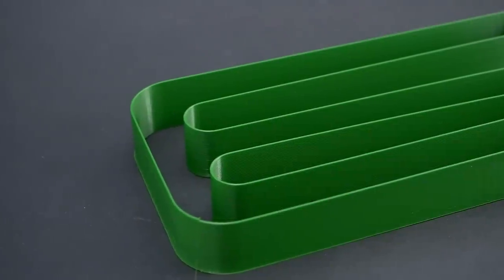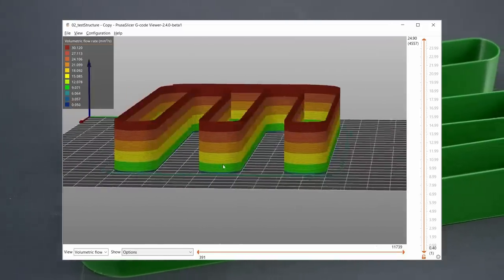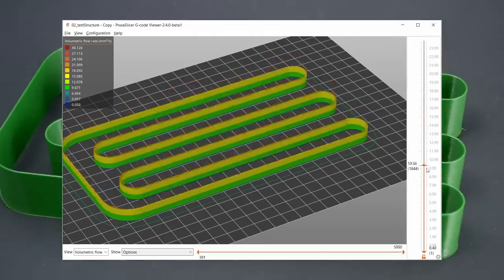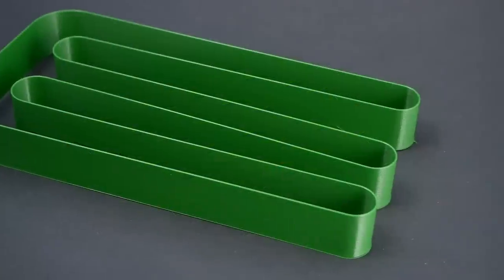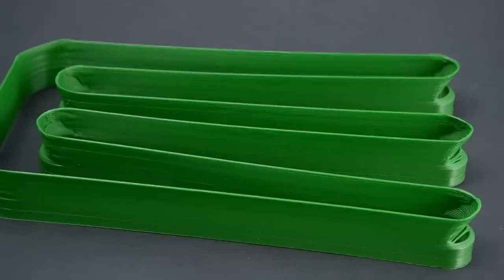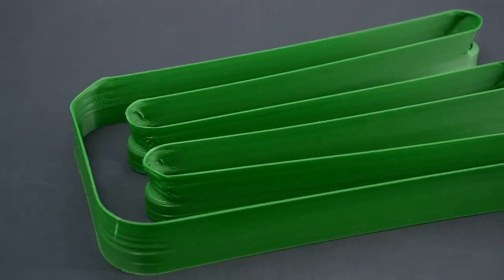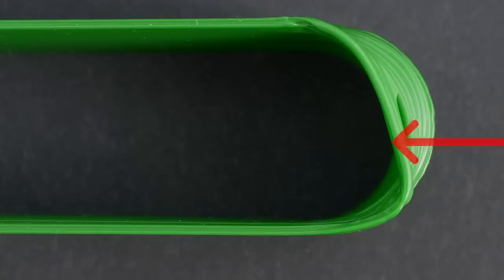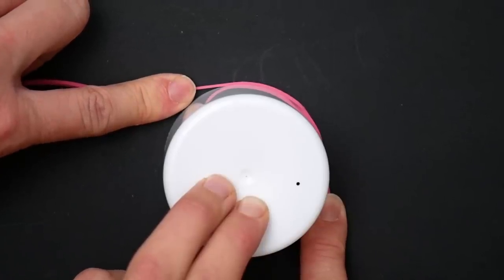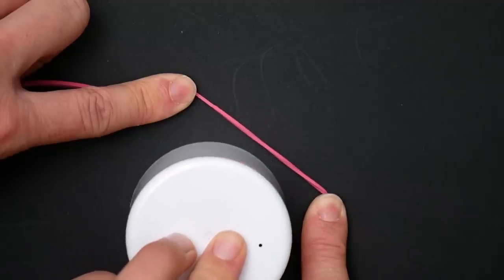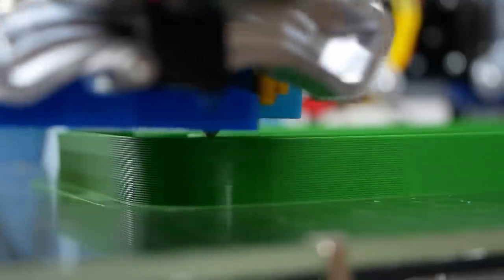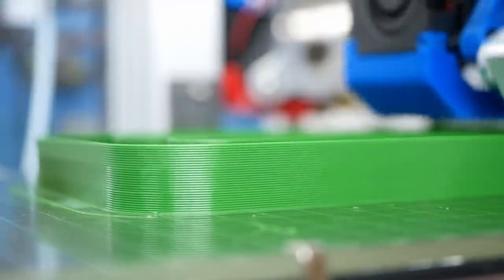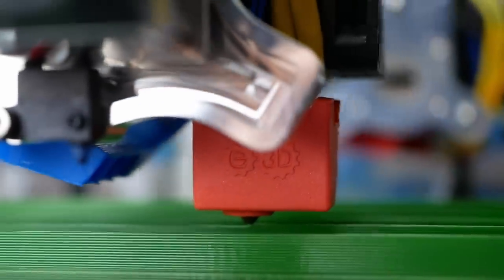To test printing performance and residual stress, I designed a meandering part that I print in vase mode at increasing extrusion rates by simply increasing the speed factor every 5mm, starting from 10 all the way up to 30 mm³ a second. Printing problems at specific extrusion rates can show in two different ways. Underextrusion because the feeder is just not capable of pushing enough material, causing thinner extrusions or even voids in the walls. Then there are printing problems caused by the internal stresses, especially seen at the corners. If the extrusion line is pre-stressed, it tries to find a state of minimum potential energy, which I can simply illustrate by a piece of pre-stressed rubber band that tries to snap back to a short line instead of the elongated curve. Of course, cooling also plays some role here. Because if you solidify the extrusion before it can deform, you freeze the internal stresses. Since I used the same cooling solution for all of the parts besides the Volcano, the results should be very comparable though.